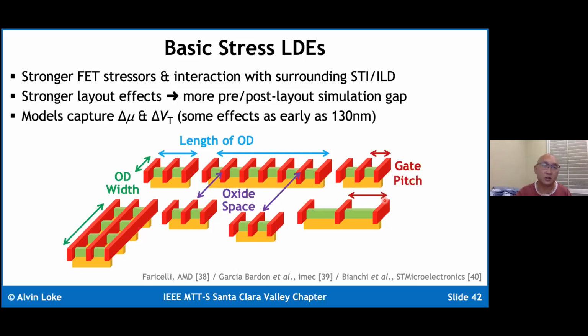Now the good news is these effects have been around since as early as 130 nanometers. And so, for instance, the LOD effect is captured. The models typically capture the change in mobility and the change in threshold voltage resulting from the change in stress.